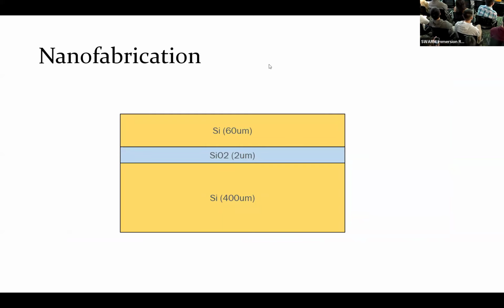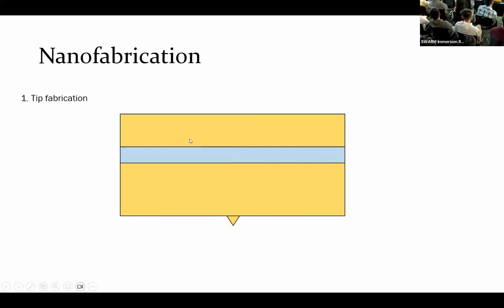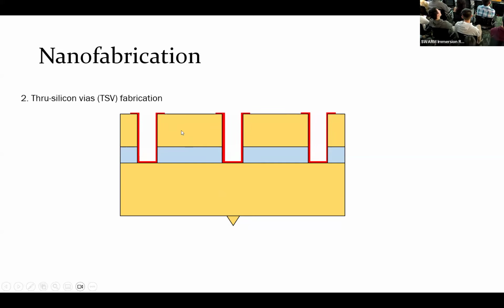And I'll briefly comment on what it takes to make these devices. Our starting point is, of course, industry standard silicon-on-insulator wafers, and we first make the tip on the backside using KOH etching. Then we developed a special process for making in situ through-silicon vias from the device layer to the handle layer. The reason for doing this is to achieve complicated functions without needing external wires. Basically we can design an in situ mini PCB, like a 2-layer PCB from top to bottom layer, and achieve these complicated functions.